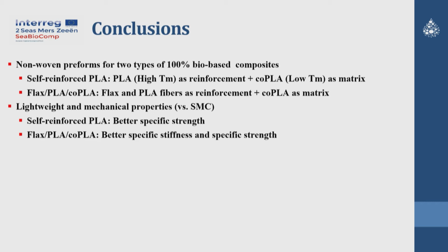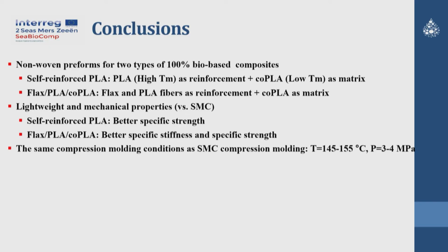So we could obtain significant weight reduction, and we can use the same equipment and same mold as for the SMC. We don't have to develop a new mold or new manufacturing equipment. The manufacturing process cycle time is a little bit longer than the conventional SMC compression molding, but nevertheless, it is much shorter than vacuum infusion and VE-RTM.